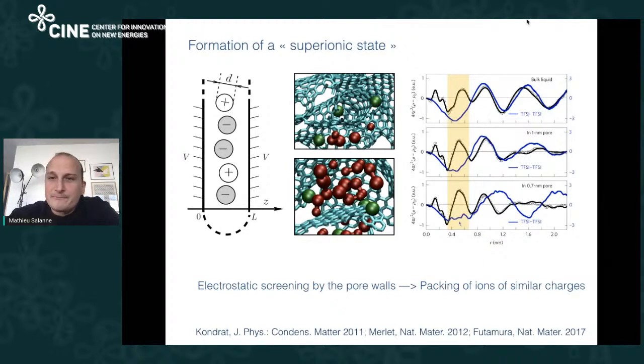if you look at the data on the right, you have the correlation between ions inside the bulk liquid, that's the first plot, inside a 1 nanometer pore, the second plot, and inside a very small pore of 0.7 nanometer. And the important plot to look at is the blue one because it corresponds to the anion arrangement. And if you focus on the yellow line at around 0.4, 0.6 nanometers, you see that you have a minimum in the bulk liquid. So this means that they don't like to be close to each other. In the 1 nanometer pore, it's still a minimum, so you still have anti-correlation between anions. But in the 0.7 nanometer pore, you start to have a kind of pre-peak, and this pre-peak is clearly a signature of the formation of this superionic state.